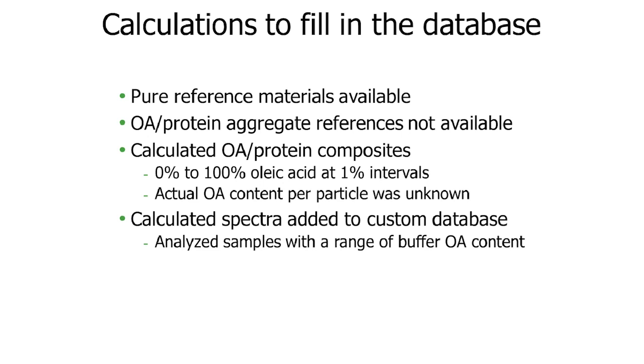While we had the pure reference materials, that oleic acid and protein, we didn't have access to any mixed references for oleic acid and protein aggregated in known ratios. Instead, we filled the reference database with composite protein oleic acid spectra that were calculated across a full range of ratios. The actual oleic acid content per particle that we are going to find was unknown going into this, so we created that full range of composites calculated from 100% oleic acid to 100% protein at 1% intervals. This reference database was then used to analyze aggregated samples that had a range of buffer oleic acid content.